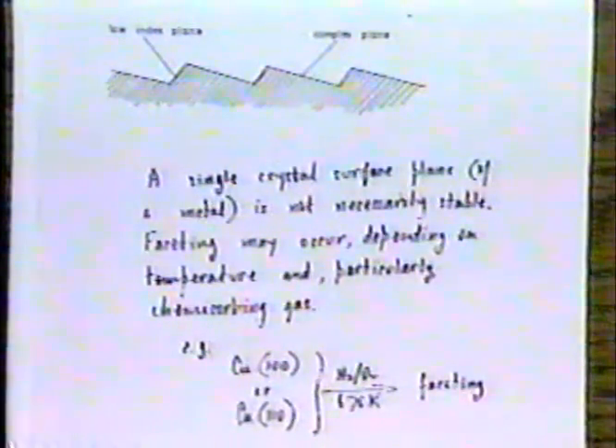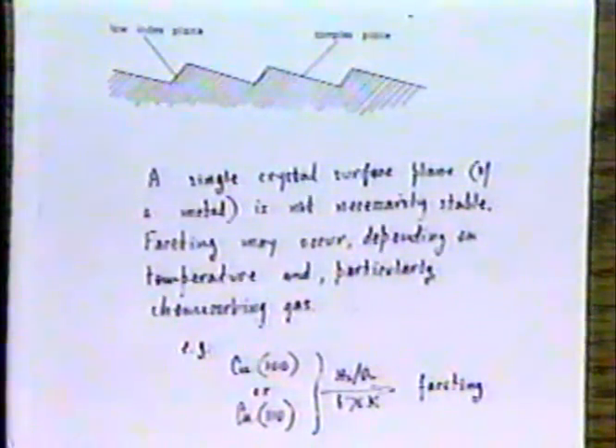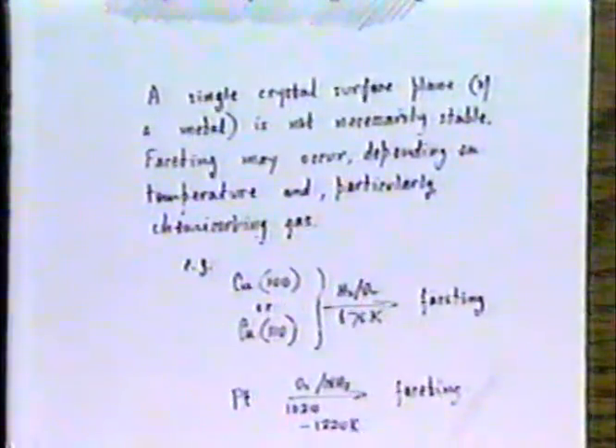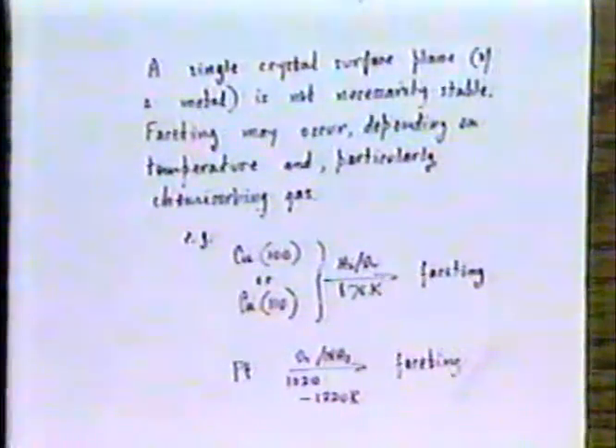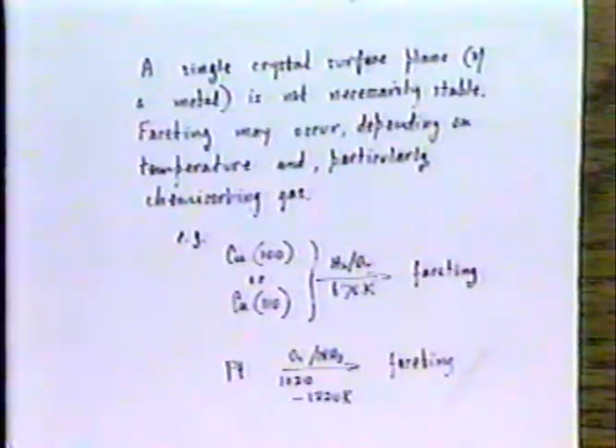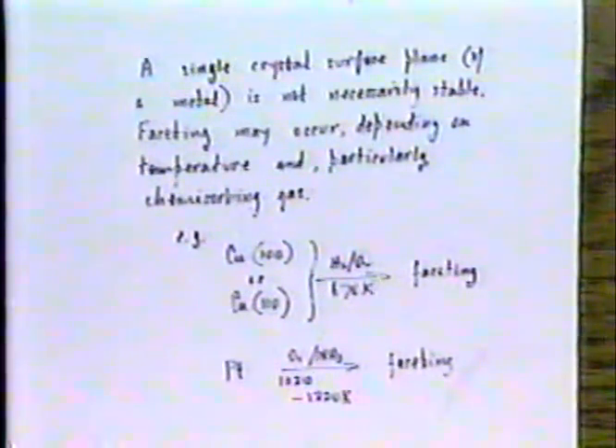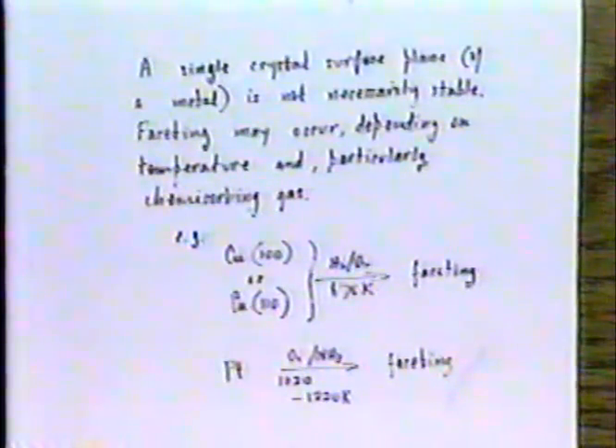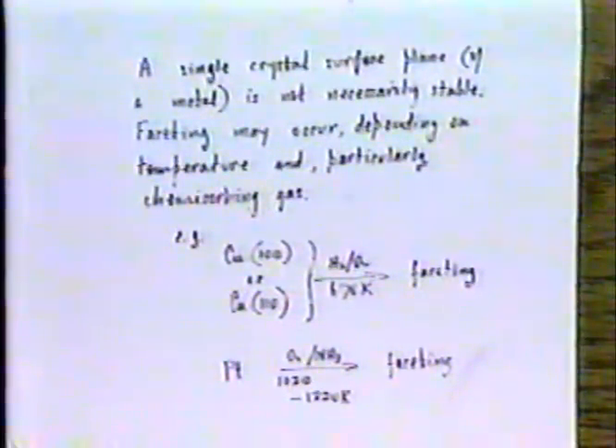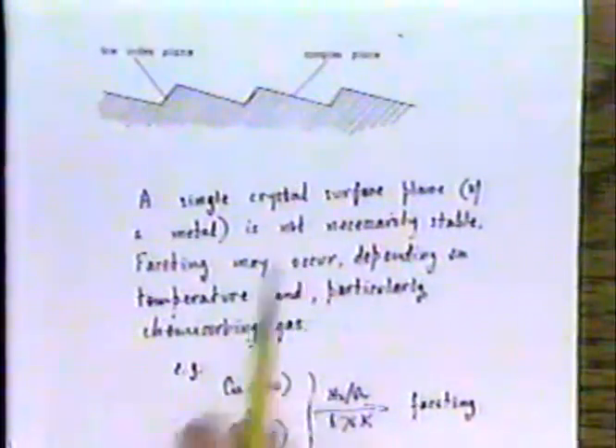Just in passing I might point out, there's been a great deal of work of this sort done with faceting of platinum in the oxidation of ammonia. As you might expect, it's an industrial process of considerable importance. Even if you start with a polycrystalline wire, which is traditionally the style of catalyst that's been used for that process, one always gets extensive surface rearrangement of this style, and the structure of the working catalyst is almost always not what you think it is, because it's broken up into a rough sort of structure of the sort shown at the top of the diagram.